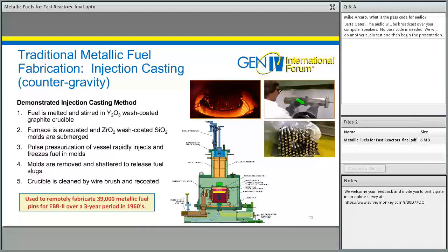You just mechanically break the quartz molds off of the metallic fuel pins. They're typically called slugs. You section them to length, and then you use them to fabricate your metallic fuel pins. The crucible is generally reusable a number of times, but it does have a reaction product on it that has to be removed by typically wire brushing, has to be recoated, but the crucibles typically are used repeatedly.